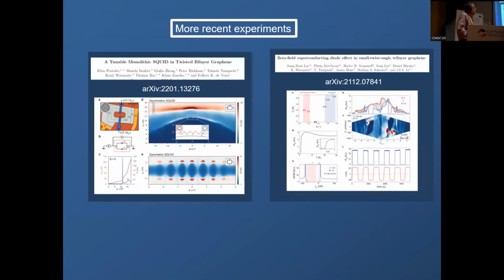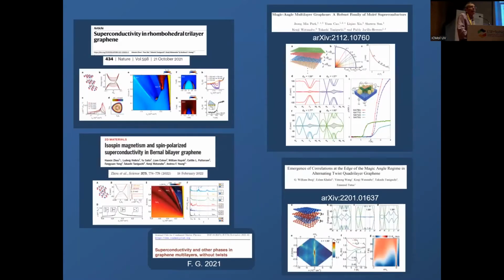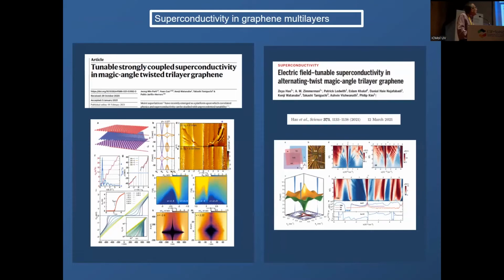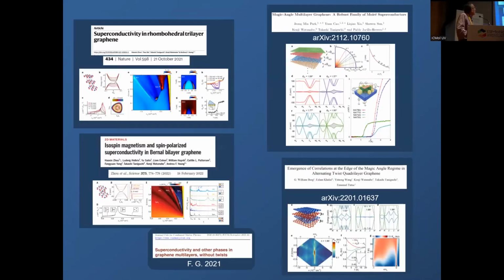Now people have gone from twisting 2 layers to twisting 3 layers, 4 layers, 5 layers, and all of them seem to show superconductivity, insulating phases, and so on. So it's a very interesting field, growing rapidly and full of surprises. Beyond the first experiments, which already were a big surprise for everybody, nowadays people have noticed something even less expected: superconductivity in regular graphene samples, in tri-layers and bilayers with no twist at all.